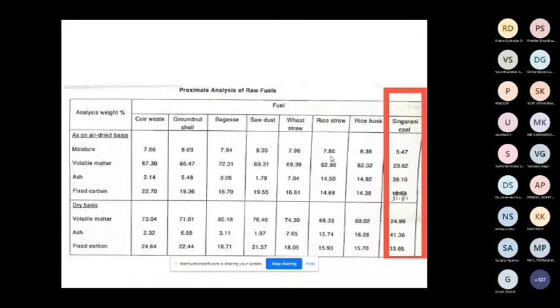See here, I have given the proximate analysis of 7 biomass fuels. The last one, within the red, is the coal analysis given for comparison. For coir waste, groundnut shell, bagasse, sawdust and wheat straw, the moisture content on air dry basis varies around 7 to 10%: 7.8, 8.69, 7.94, 9. Mostly below 10% moisture on air dry basis for all 7 biomass fuels. Coal is similar, at 5.47 on air dry basis.